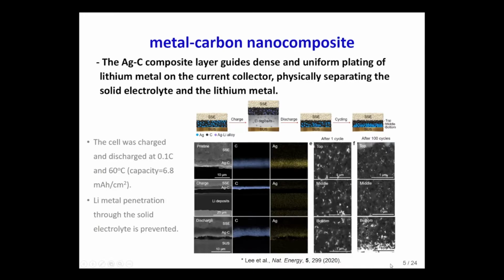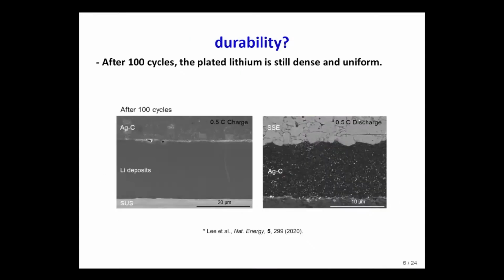With this design, the probability of lithium metal penetration through the solid electrolyte is significantly reduced because the silver carbon layer is blocking the direct contact of lithium metal with the solid electrolyte. This process can be repeated many times. Even after 100 cycles, we can still see a very dense lithium deposit after the charge, and it is completely cleared after the discharge.